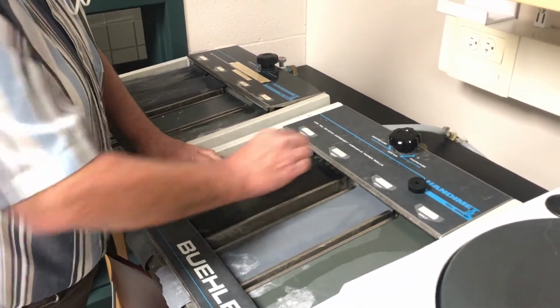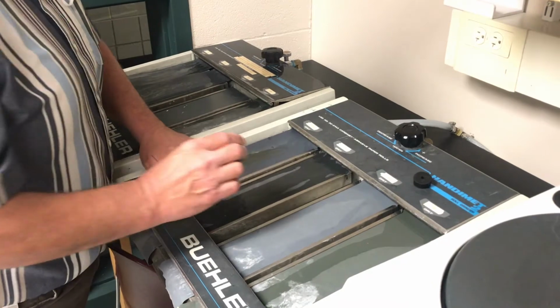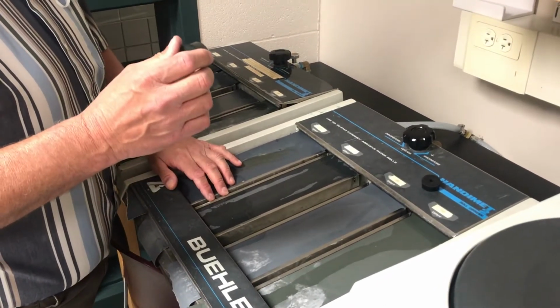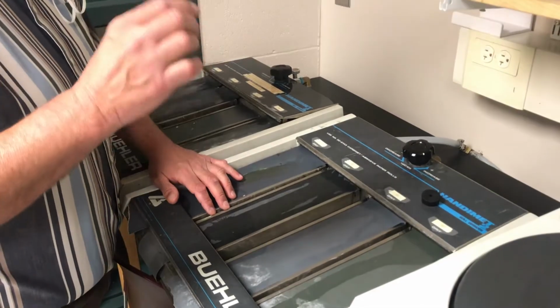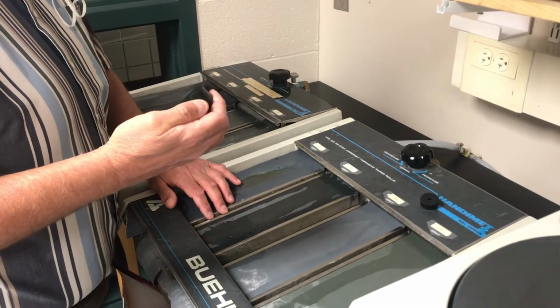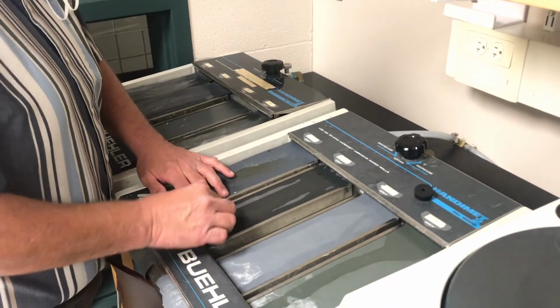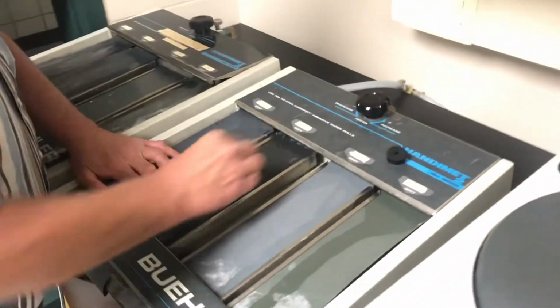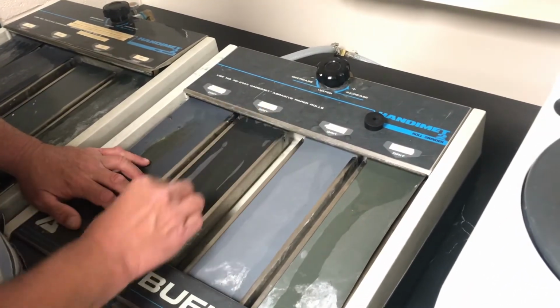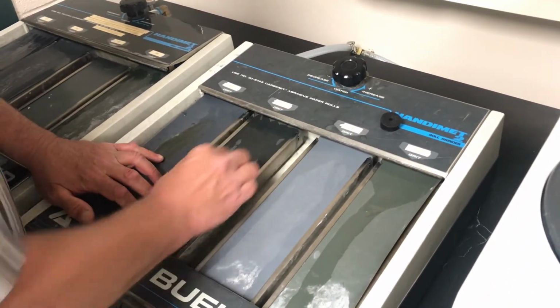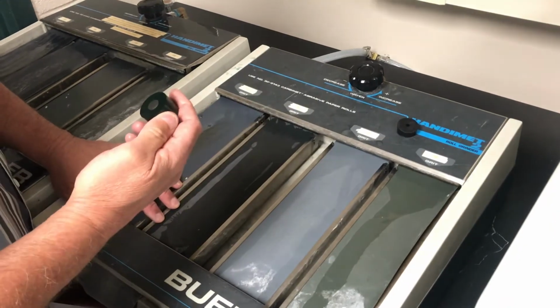Say 20 strokes. Now you turn your sample 90 degrees because you want to see if all the scratches are in the same direction this way. And that's a good trick to make sure that is the case. So just turn your sample 90 degrees as you go from one paper to the next, and that way you can use your sample to see your progress.